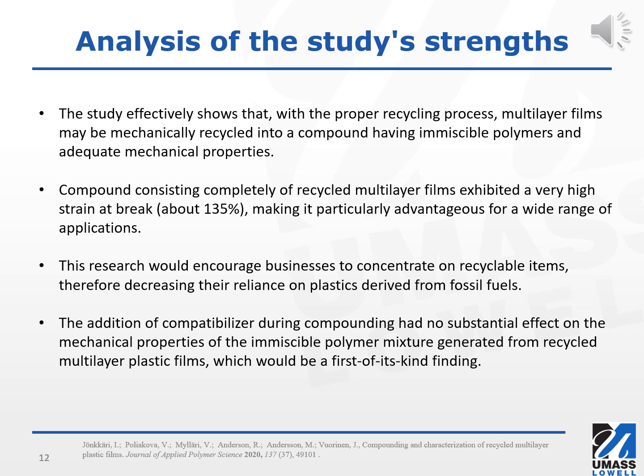Besides, a compound made entirely of recycled multilayer films demonstrated a high strain at break, which is around 135%, which made it very useful for a variety of applications, and this was particularly remarkable as well. This research would encourage industries to focus on recyclable things, which would result in a decreased reliance on plastics obtained from fossil fuels by those businesses. Besides, this would be a first of its kind discovery if it were confirmed that the addition of a compatibilizer during compounding didn't have a substantial effect on the mechanical properties of the immiscible polymer mixture that was formed from recycled multilayer plastic films.